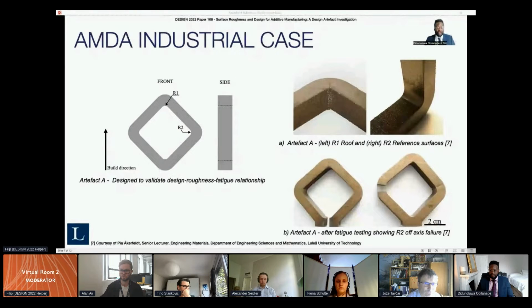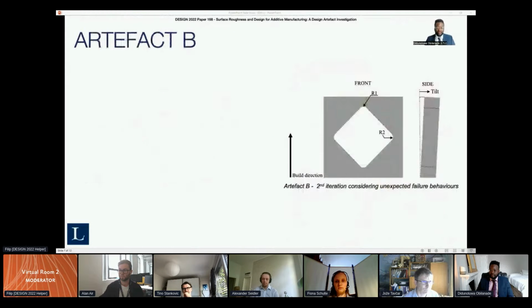Additionally, shown in Figure A right, where the artifact arm design changes from the R2 radius to an unsupported 45-degree overhang surface, a transition line from smooth to rough surface was noted, causing the point of fatigue failure at R2 to occur off-axis, as shown in Figure B right.